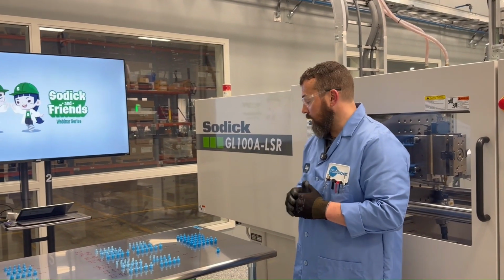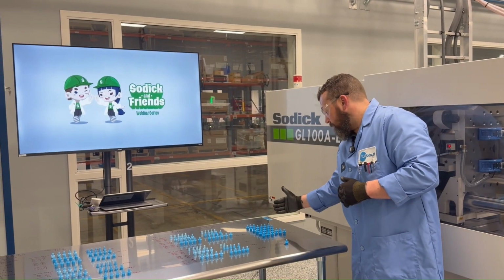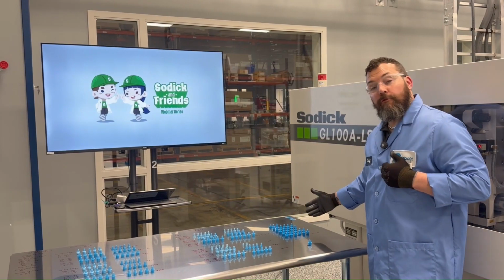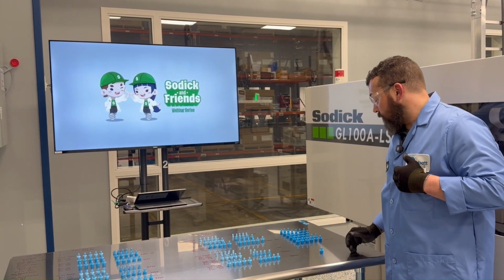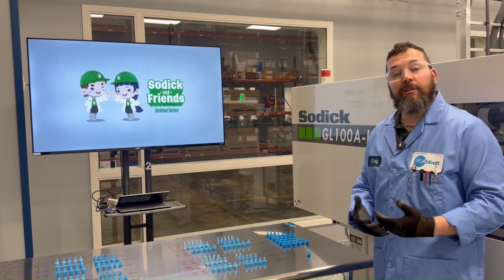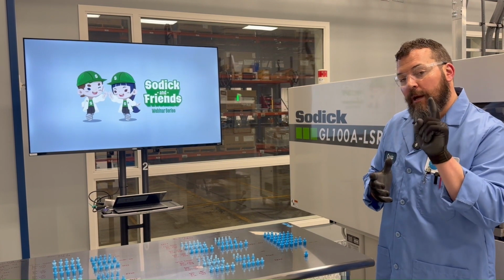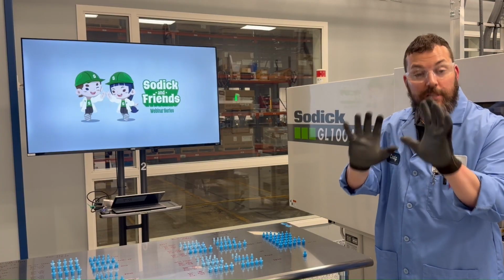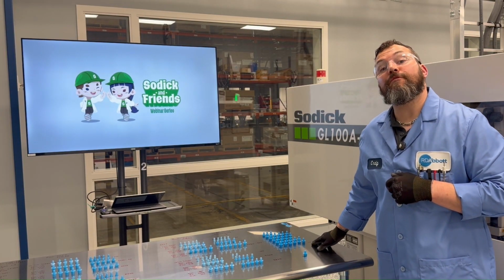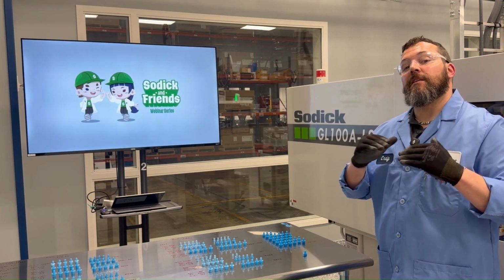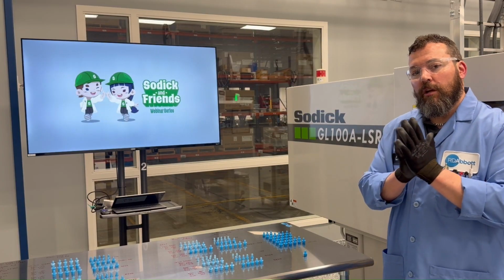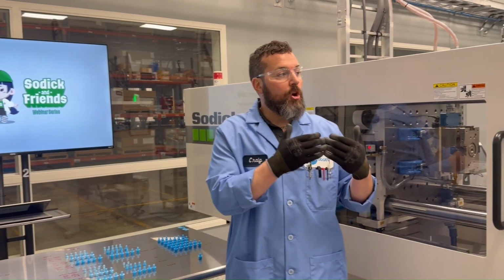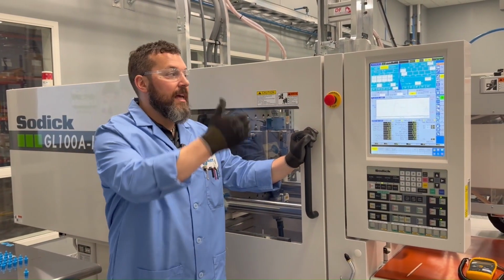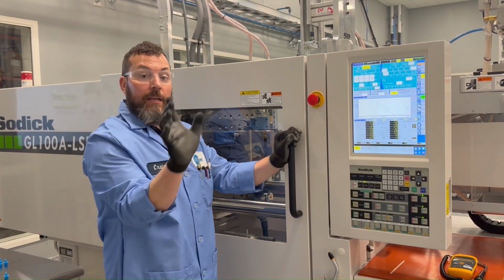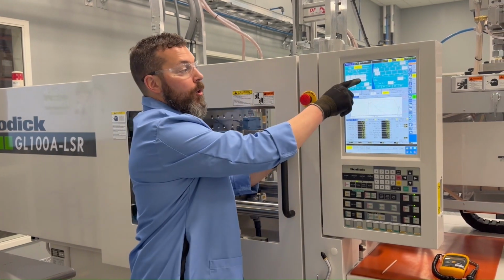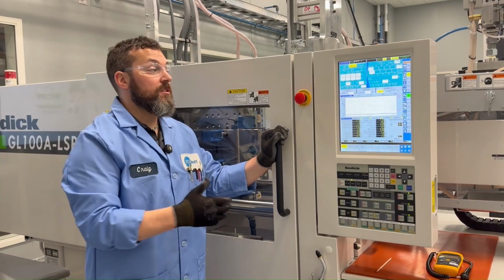velocity, injection speed. So increasing my hold pressure, I'm not really seeing a big difference. 1.44 grams, 1.47, 1.50, 1.54. In this last profile, taking the pressure up to 2000 PSI, only at 0.2 seconds, apologize. We're 1.57 to 1.59. We're bouncing. That's telling me we're inconsistent. Remember I talked about the compressibility of the material. That pressure, no matter how high that pressure is, we don't have a lot of time there. So we have to increase that time to see what happens. So right now I have my time at 0.4 seconds and my hold pressure at 1500 PSI. We're gonna run some iterations to see what this looks like.